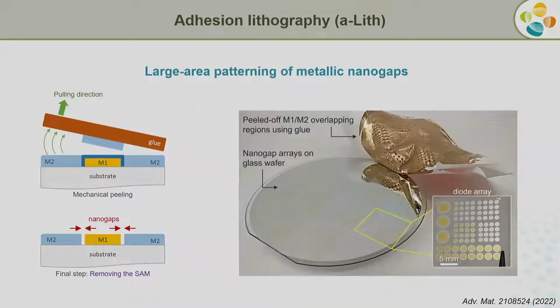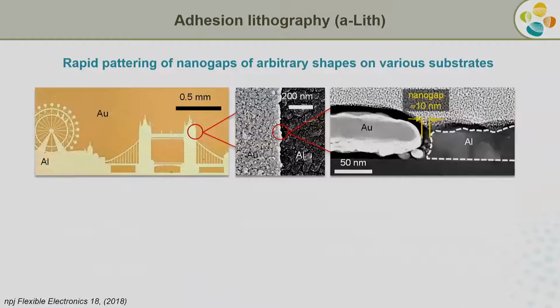So we've been developing patterning technologies, and this is a few slides I have left, which combines essentially large area processing capabilities with the ability to shrink key device dimensions down to a few nanometers. One of the examples is adhesion lithography, a-Lith, we say. We only use very relaxed lithographic steps, which are scalable to meter squares of substrates. So it's absolutely inexpensive. And then in combination with a bottom-up technology, like letting nature take charge of how these materials self-assemble in pre-programmed areas, we can define key feature dimensions down to 10 nanometers. So essentially, this is two metal electrodes we have patterned using this technology, only 10 nanometers apart from each other.